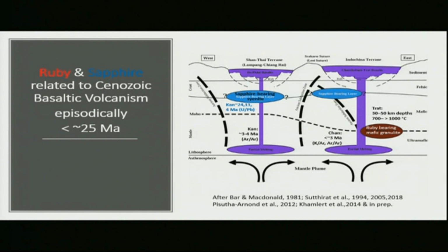What's interesting is that in the Trat area, which is now very well studied, they found that the protolith, the precursor of the Thai ruby, is actually from a different depth. From calculation, they found that it was at a depth of about 30 to 50 kilometers, much deeper. So it's probably down to the lower crust or upper mantle. And temperatures were about 700 to more than 1,000 degrees. It probably formed earlier. This is the protolith of the ruby-bearing rock, and they found that it is hosted in mafic granulite, which is a different kind of rock, a very basic type.